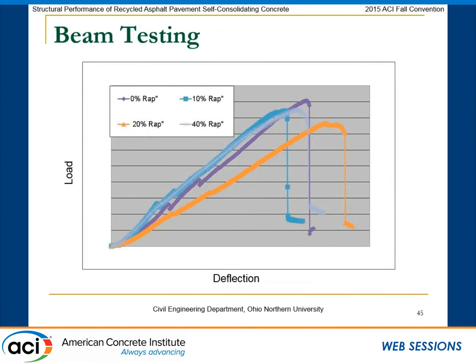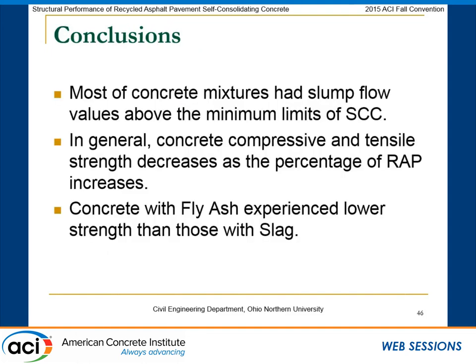And then we did the three-point test for the beams, and we have 21 of these, but I'm showing you a sample here. So we saw that when you introduce RAP, you have a reduction in your load carrying capacity. As you can see here, the 20% RAP is just showing a different behavior than the rest of the beams. But in general, RAP would decrease your load carrying capacity.